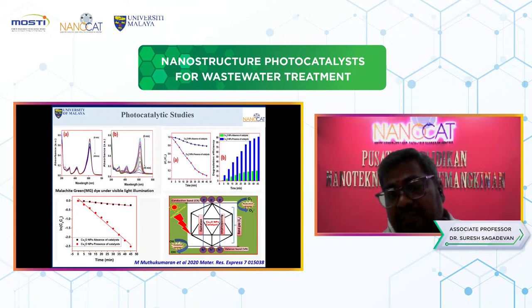You can see that in the time interval of 0 to 45 minutes, from the figure it can be seen that there is no significant change in the reaction in the absence of catalyst. But a significant decrease in the malachite green dye concentration was observed in the presence of the catalyst, and this effect increases with the reaction time. You can see that the degradation percentage is highest, above 90%, in the presence of catalyst. In the absence of catalyst it is very low, below 20%. And also we calculated the R squared value, the coefficient of correlation, using the kinetic plot. This is the mechanism of how the electrons and holes recombine when visible light is illuminated.